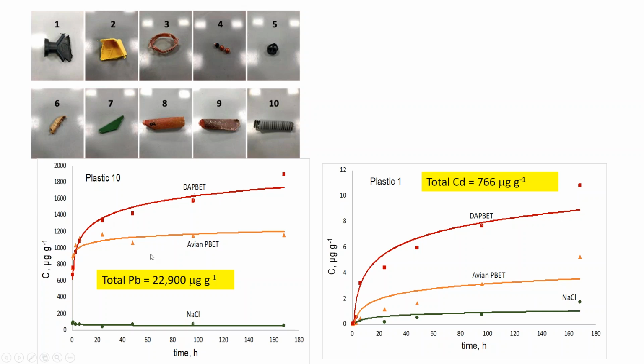This is cadmium here, this is lead here. Take a look at the lead, for example. We have 22,000 or 23,000 micrograms per gram of lead in that sample. This is plastic 10 here. And we see that after 150 hours or so, about 2,000 micrograms per gram, or almost 10% of the entire amount of lead in this comes out when it's exposed to acid and some sort of fish oil, which is a simulated part of the animal's diet.